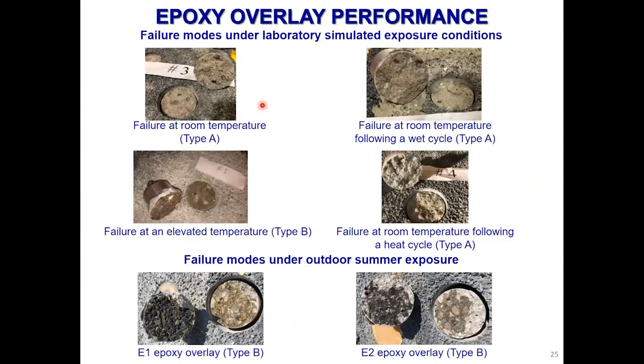Failure-wise, typically we like to have type A failure in concrete, which we see under room temperature as well as under wet and dry cycles. But under elevated temperature, we see the failure at the interface. Once we let it cool down, it reverts back to failure in the substrate. That's a good sign. And outdoors during summer, under elevated temperature, we also see the failure at the interface.